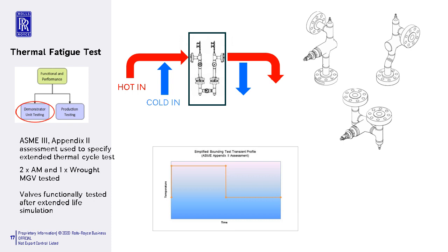So in support of this test, we carried out an ASME 3 Appendix 2 assessment, specifically to work out the loadings for each of the thermal cycles and also the number of cycles to apply, to ensure that we significantly exceeded those experienced during plant operation. And this was really up to a factor of around 10. The test train was then fitted to a rig, which had a hot loop and a cold loop, which could be valved in and out of the test train almost instantaneously in order to introduce the thermal cycles a number of times.